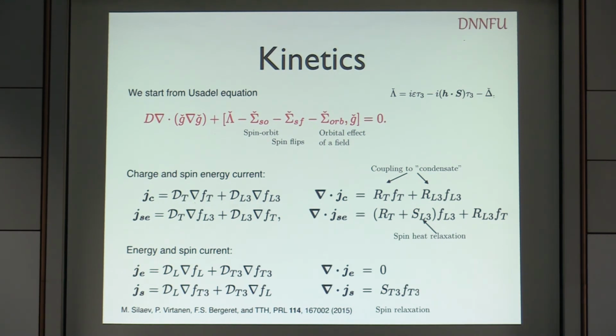Now there are four of these Boltzmann equations, and they come in pairs. One pair couples charge and spin energy, and one pair couples energy and spin. There are diffusion terms coming from the first term in the Usadel equation, and then there are relaxation terms coming from here. Those relaxation terms are, for example, related to spin-flip scattering and so on. In the Boltzmann equation, relaxation terms are called collision integrals.